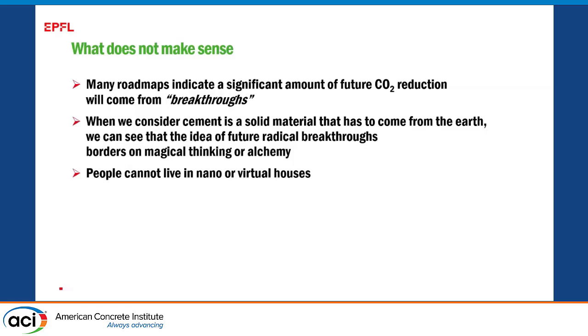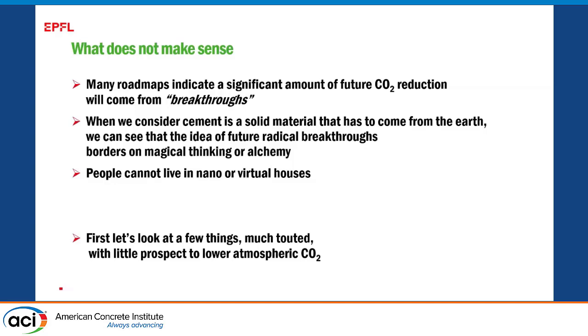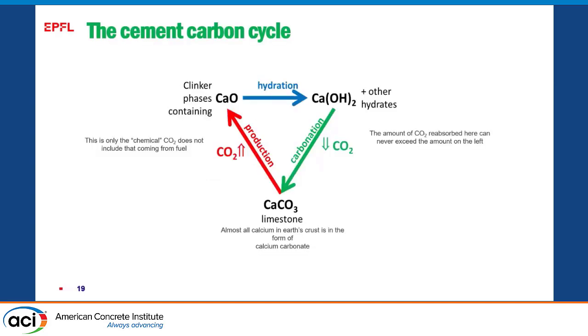And then we can't really shrink our houses. This is another obstacle we have because a lot of the gains we've made in the efficiency of producing cement has actually been wiped out by the people wanting to have larger houses to live in. And there's a lot of startups out there which are trying to deny this basic cycle here. We use limestone to produce cement. It gives off CO2. It then hydrates, gives us all these nice solids, which gives us durable concrete. And it will recarbonate over time, but clearly the amount of CO2 that can be reabsorbed can never exceed the amount of CO2 that was given off.